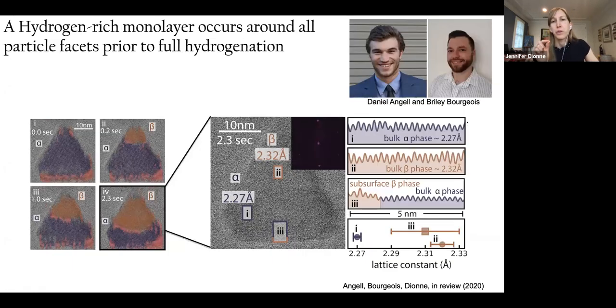We wanted to know if those low resolution STEM images that indicated there was surface wetting or surface hydrogenation actually occurred when we could get atomic scale resolution in an environmental condition. And recently, thanks to advances in direct electron detection and Gatan's K3 camera, we're able to do environmental imaging at atomic scale resolution. Here I'm showing you an example of one of those single crystalline prisms where you can see that, again, the hydrogen enters from the tips, but there is actually this subsurface of hydrogen. And if you look at the lattice fringes along each of the corners here, I'm just showing you one of them, but we actually wind up having confirmed subsurface beta phase within the first few monolayers around the entire prism.